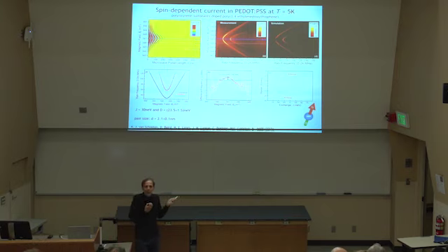And that shows now the sensitivity of this kind of current detected spectroscopy. We see a deviation somewhere in the hundreds of kilohertz range, definitely below megahertz. And we know this reflects now the spin-spin interactions. That could be exchange, that can be dipolar. And now if you dig deeper and take these values that you measure here apart, by using the spectral dependence of this deviation, then you can narrow it down to a range for J. So J has to be smaller than 30 nanoelectron volt. And D has to be around 23, 24 nanoelectron volts.